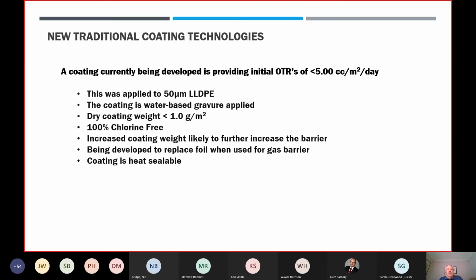Just to give you some details about this one, those figures were derived after it was applied to a 50 micron LLDPE. The coating is water-based and gravure applied. Dry coating weight of about 1 gram per square meter. There is absolutely no chlorine in this material. And we believe that increased coating weight is likely to further increase the barrier. And it is currently being developed to replace foil when used for a gas barrier in packaging. And the final thing is the coating is actually heat sealable as well.